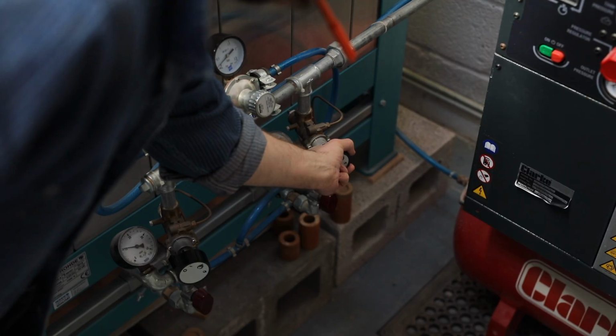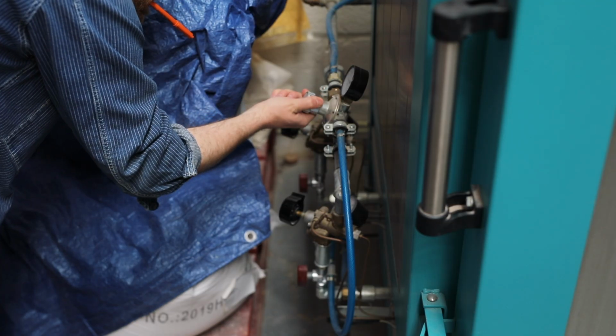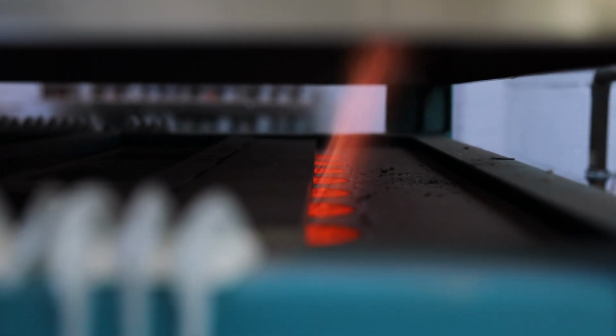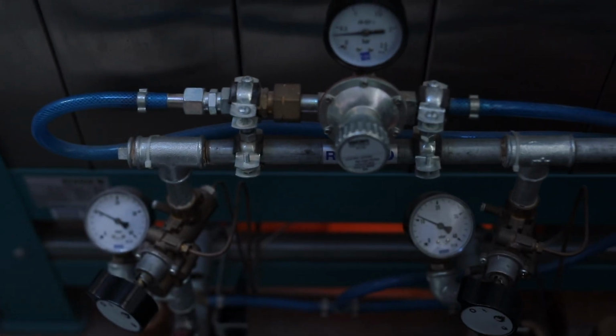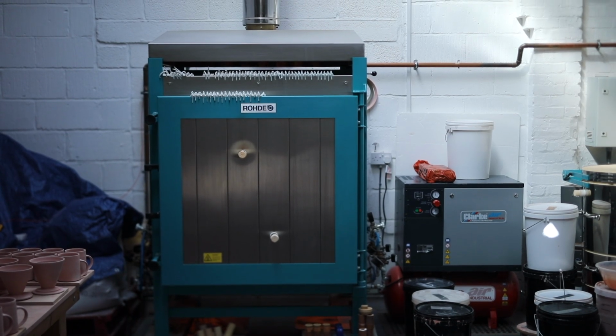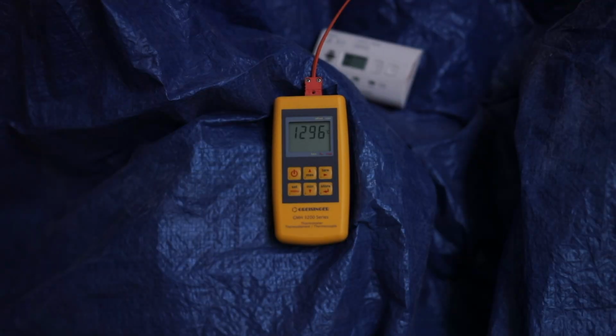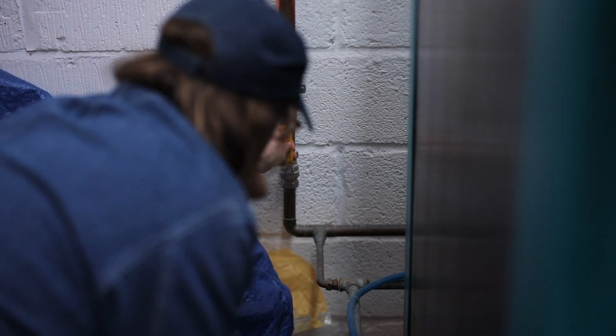Every 30 minutes I check the kiln and gradually increase the temperature. Unlike my electric kiln, this one is fired completely by hand, controlled by dampers that cover the flue and all the valves down here. You know a strong reduction atmosphere is happening inside when these plumes of flame start to emanate from the flues in the back of the kiln. And once the correct temperature has been reached and cone 10 is fully bent over, the gas can be switched off, the firing now complete.